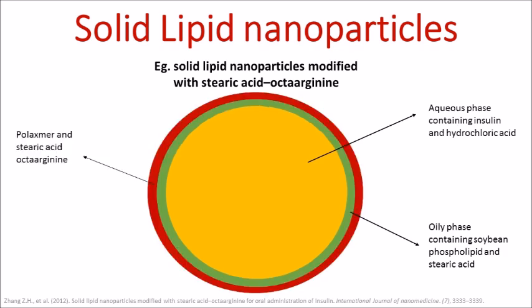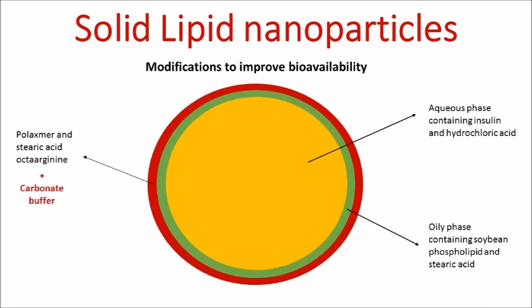Then the emulsions are poured into poloxamer and stearic acid octaarginine solution under continuous stirring at 500 RPM for 1 hour in order to form the solid lipid nanoparticles. The untrapped drug and the adjuvant are removed by filtration, and the formed solid lipid nanoparticles are filtered and lyophilized. This is the main composition, which reduces the degradation by pepsin to some extent so that the insulin remaining is 54.7% after 1 hour compared to the insulin standard solution. Thus, we can add carbonate buffer to improve the formulation stability in the stomach.